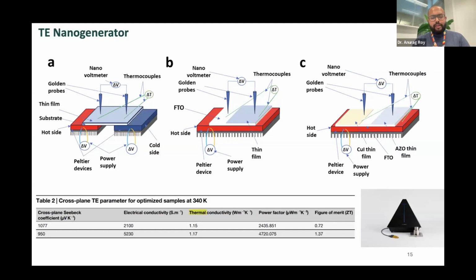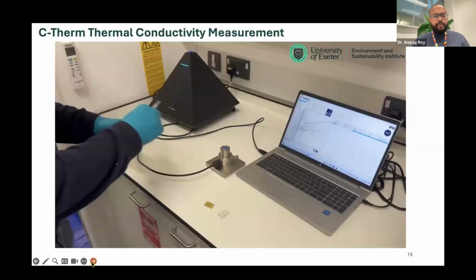And that value corresponds to 1.15 for aluminum-doped zinc oxide thermal conductivity, and for copper iodide it is 1.17. That leads to the figure of merit 0.72 for zinc oxide and 1.37 for copper iodide respectively.